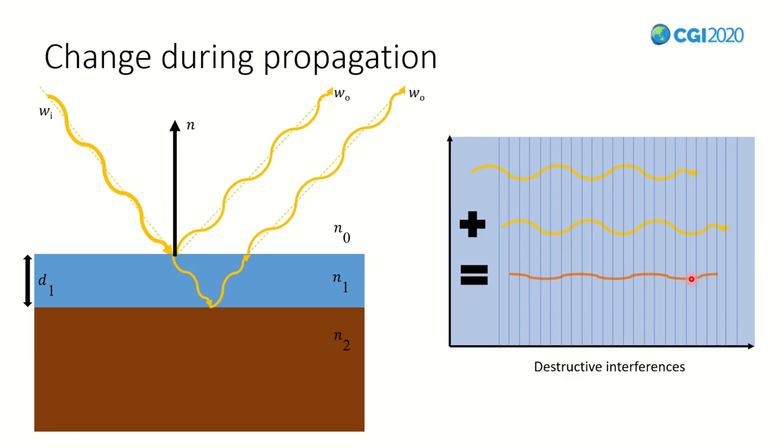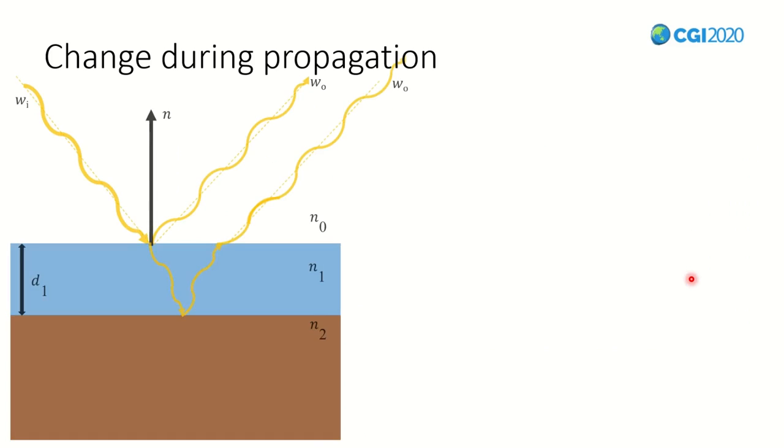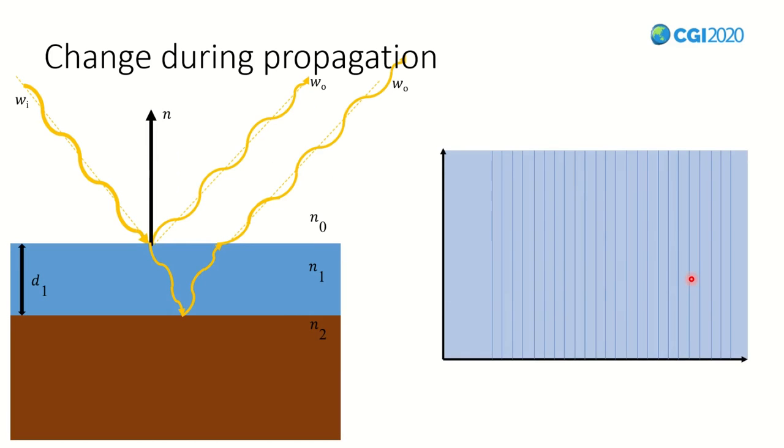So now let's see what happens with the thickness. Well, if we increase the thickness, the same thing happens. We have a first wave that is immediately reflected, and we have a second wave that goes through the coating back and forth and back in the same direction in our first medium. But because the coating is thicker, the delay, so the time to travel through the coating, increases. So the translation of our curve to the right increased as well.